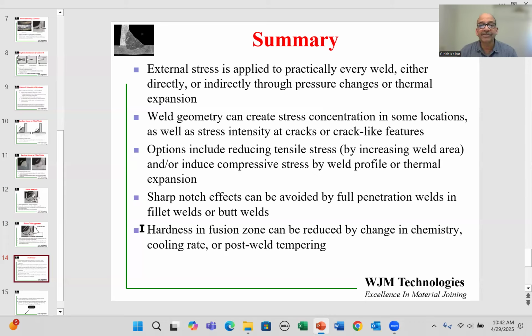And of course, you can change the chemistry of the weld or the process to reduce the hardness, such as say post-weld tempering or preheating. So there are many techniques which you can use to extend the life of your weld if your weld is found to be susceptible to crack growth, leading to a lower life than expected.